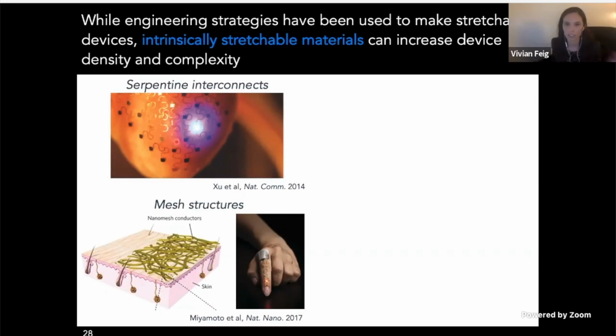So here, John Rogers uses these serpentine interconnects, and then Takao Someya likes to use these kind of mesh-like structures. But the limitation with this engineering approach is that it's really highly dependent on the dimensions of your device, and you also typically need pretty large amounts of distance between those rigid islands to accommodate strain. And so there's an inherent limitation there in terms of how complex or dense you can make these electronics.